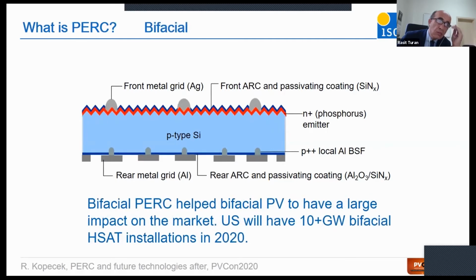The bifacial version is also possible with PERC. That means that you are not fully printing the aluminum on the rear side, but printing a grid. And actually the bifacial PERC helped the bifacial photovoltaics to get unchained. And now in the US we will have more than 10 gigawatt bifacial horizontal single axis tracking installations in 2020.